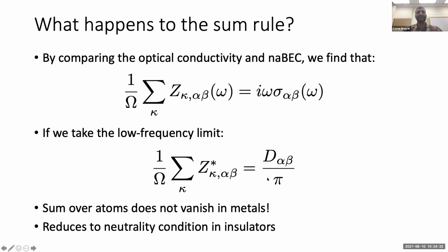So we can see from this expression that the sum rule of the Born effective charges, so the sum of the Born effective charges, will not vanish in a metal because the Drude weight is always finite. And we, of course, recover the charge neutrality condition in insulators because by definition, the Drude weight vanishes there. So we consider this a generalized Born effective charge sum rule.